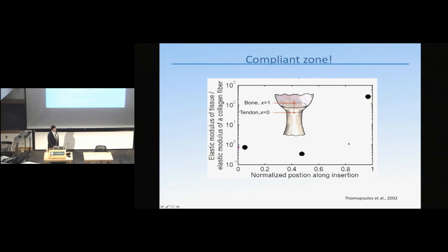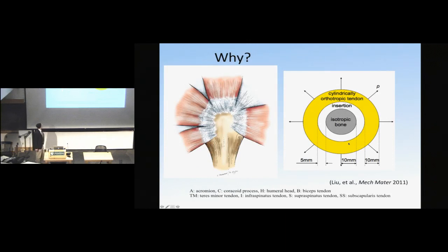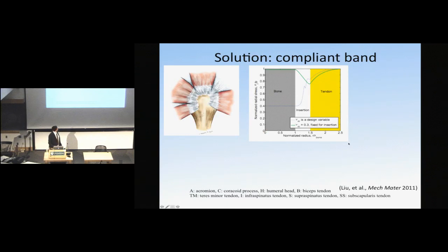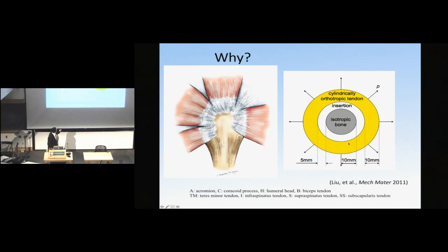And so we did some simple optimization analyses to get a sense of what this might do. This is an admittedly very crude model. We're taking this humeral head and replacing it with this linear elastic 3-band model just to get intuition for why this might be optimal. And it turns out that a gradient insertion is capable of knocking out the stress concentration entirely. So there are 3 bands, and we're looking at the stresses in the tendon, the insertion site, and the bone, and the stress concentrations show up here between the two, in the region where there's the greatest mismatch, and then also the exterior.